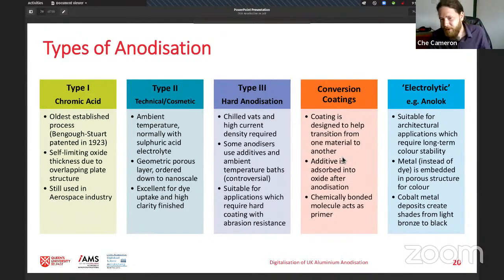Conversion coatings I mentioned, so instead of sealing or dyeing the pores, different additives are presented to them, and they are adsorbed into the oxide. So they make a chemical bond, a very, very strong bond to the surface of that aluminium oxide. And then that chemical that has been bonded in acts as a primer for whatever your next coating is, hence the conversion. It helps you to move from one material to the next.